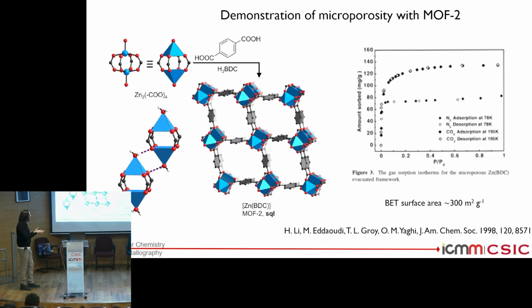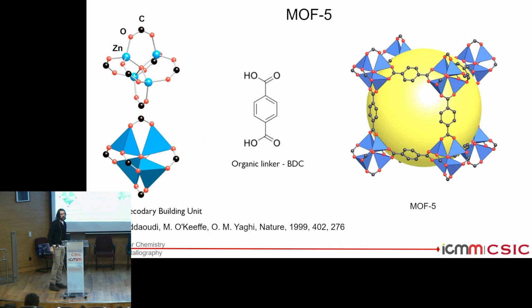Okay, so you can compare different materials and their porosity, and the first MOF surface area was reported to be around 300 square meters per gram. That was a modest value, but was comparable to, for example, zeolites and other inorganic solids. But as I'm saying, that's very relevant because it was the first time it was done for a MOF. So the MOFs are now not just some fancy, beautiful crystal structure, but they were also useful. They could also have gases coming in and out, and not only gases, but many other species.